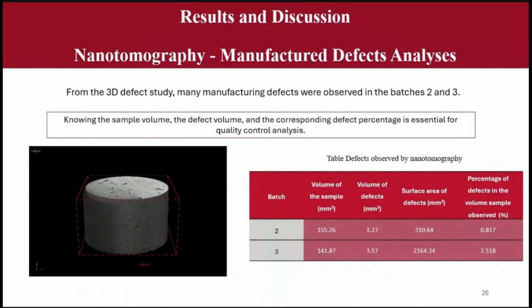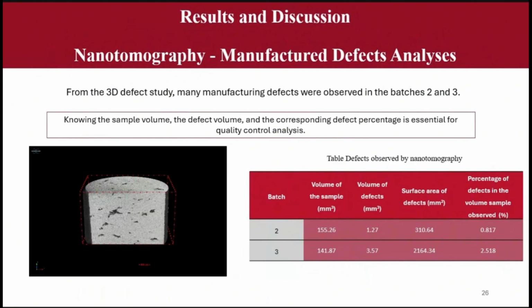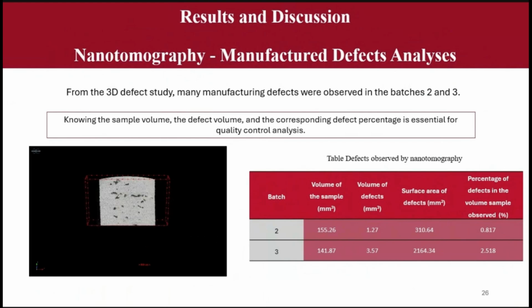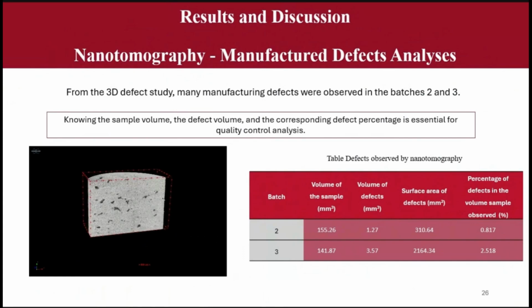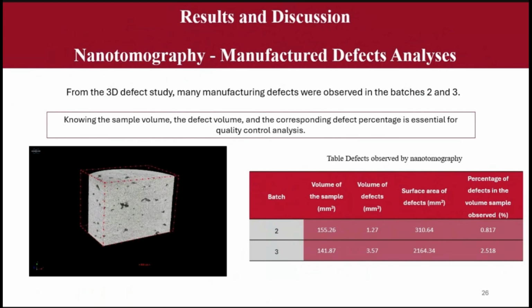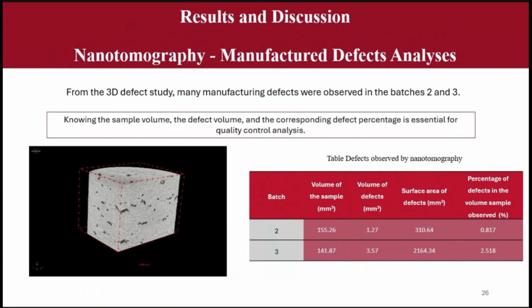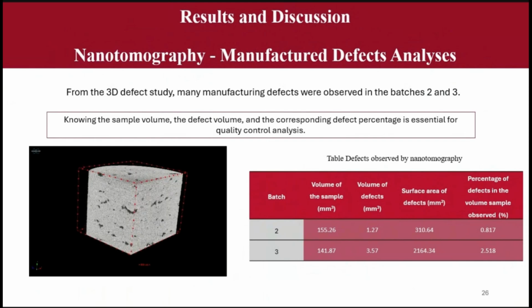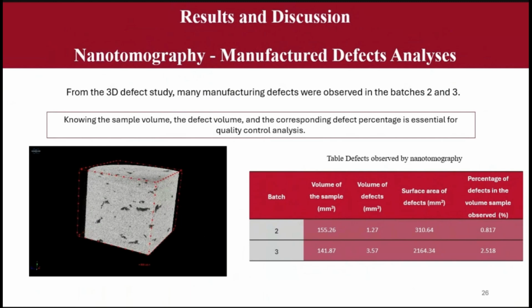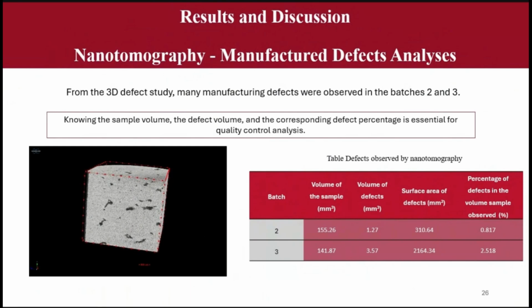From the 3D defect study, many manufacturing defects were observed in batches 2 and 3. Knowing the sample volume, the defect volume, and the corresponding defect percentage is essential for quality control. If we see the tomography image with all the treatment, we can see many pores and defects, okay? But if you see the last column of this table, the percentage of defects in the sample volume is, in batch 2, less than 1%, and in batch 3, more or less 2.5%. So this is important.